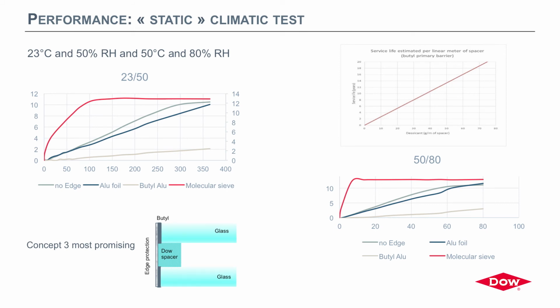It's basically putting it in the oven at different conditions of temperature and humidity. So we have here on the left 23 degrees and 50% humidity, and 50 degrees and 80% on the right. This blue curve is actually a simple bag of desiccant put in the oven as a reference. What we evaluate is the weight increase, and when we stabilize that weight increase, we assume that this desiccant has reached its maximum capacity. And so if your unit has increased by that weight amount, we will not have a desiccant that is functioning anymore. So we can see that the two concepts, the one with no edge and the one with the aluminum foil, reach full capacity of the desiccant after 350 days. The one with the butyl is still performing for the moment at those conditions.